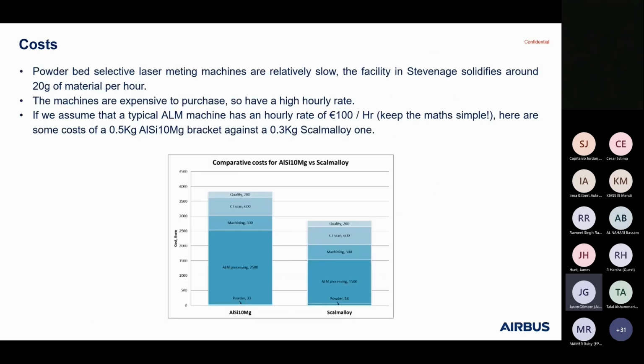So this is one of the slides I swapped out to a slightly better cost model. So let's look at the cost for an aluminium silicon 10 versus a Scalmalloy design. So the way I present this, if we look at the TMTC bracket that I presented earlier, that was aluminium silicon 10, when we had a machine in Stevenage, we were depositing around about 20 grams of material per hour. So the machines, we all know they're expensive, and if we attribute an hourly rate of around about 100 euros an hour to run that machine, we could all argue whether that's correct, whether it should be 90, 80, 120, but to keep the maths simple.